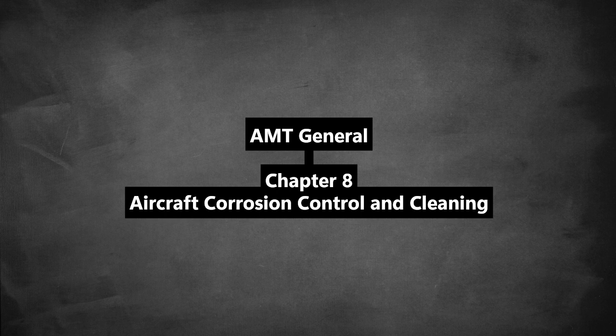Stainless steel can be quite susceptible to this, and active-passive cells occur on metals that form a protective passive film, like stainless steel or aluminum. If that film gets broken locally, say by a scratch or under dirt, the small exposed active area corrodes very rapidly compared to the large surrounding passive area. Leads to pitting.